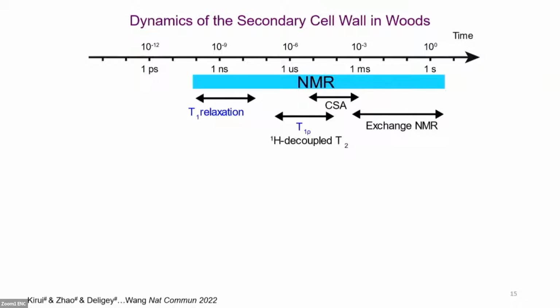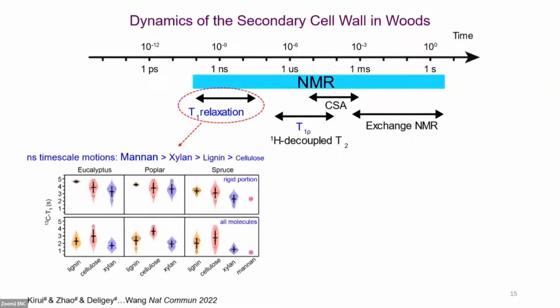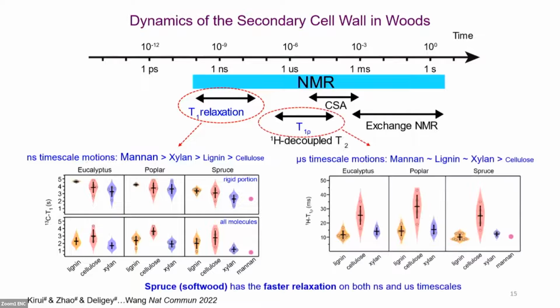Solid-state NMR can also tell us about the dynamic information in the wood samples. We can use the carbon T1 relaxation to get the nanosecond time scale motion. Here, mannan is the mobile part, and cellulose is the rigid part. And on the microsecond time scale, we can use the proton T1rho experiment to get the information. The cellulose is still the rigid part. No matter whether nanosecond or microsecond, the spruce, the softwood, always has the faster relaxation among the wood samples.